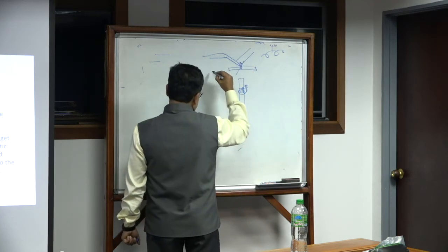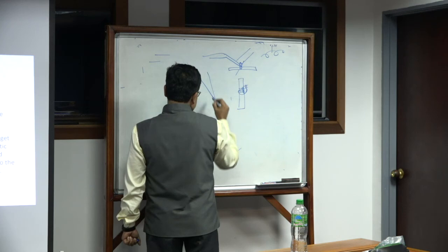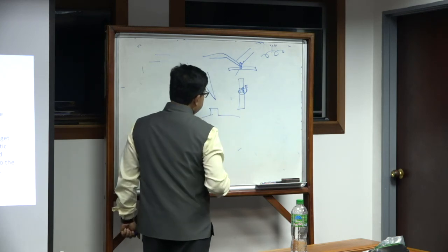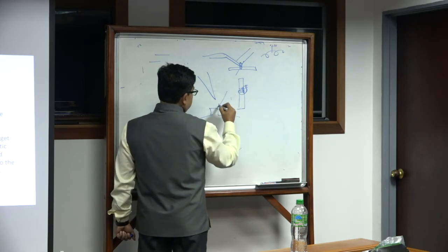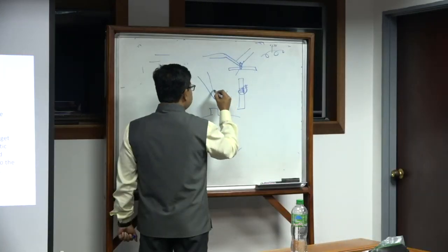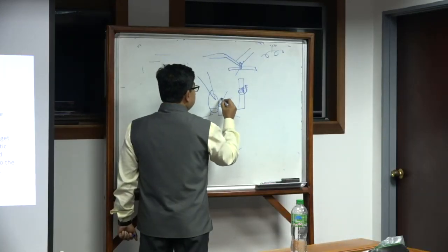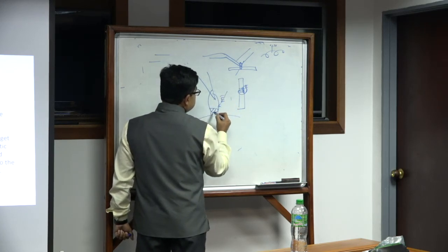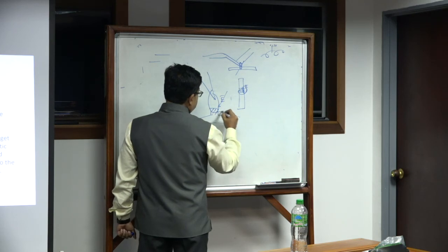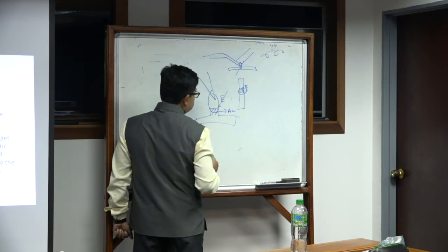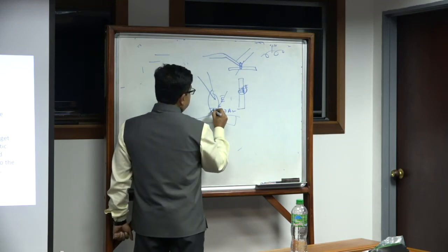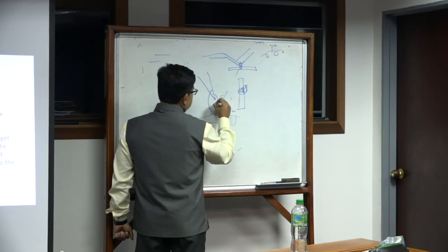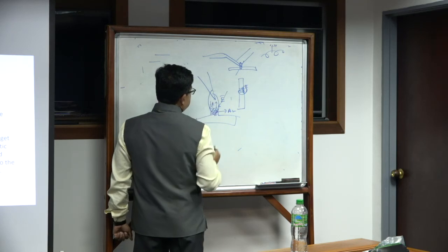Now if you take a little better picture, so you have this, that's your thing you want to image, and you excite with your light, and you create this strong near field. You create a strong electric field in between the tip and, say in this case, a gold pattern. This is your gold pattern. You create this excited surface plasmon, you create this field, and this near field is perpendicular to the metal surface.